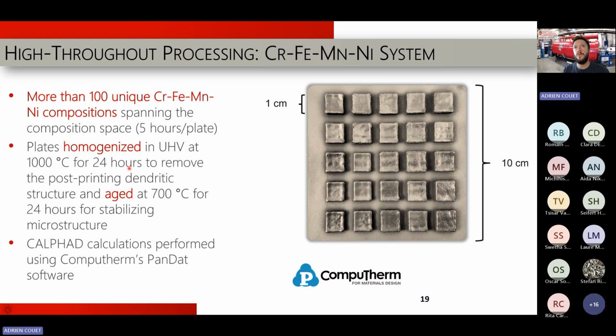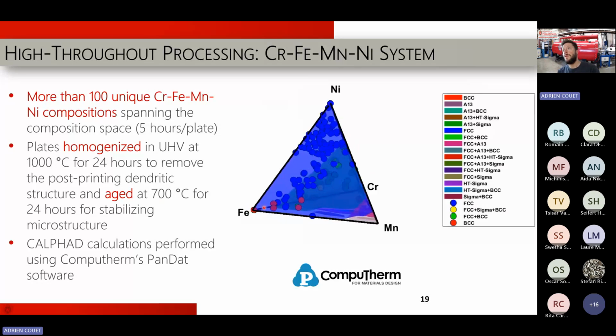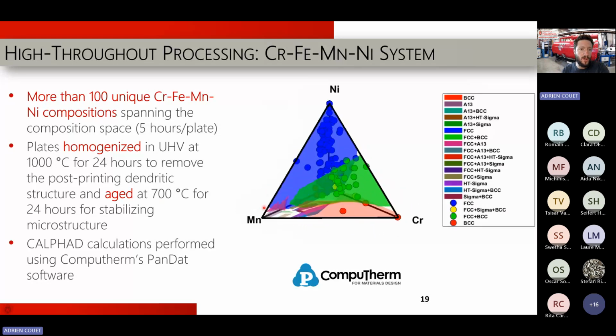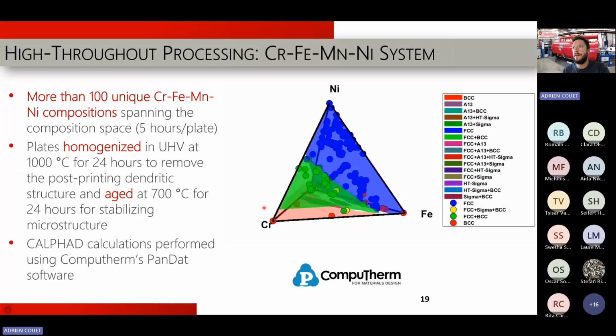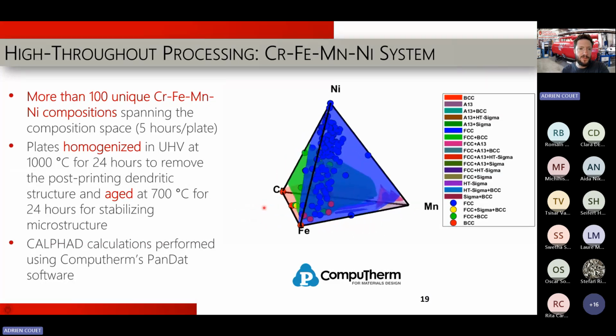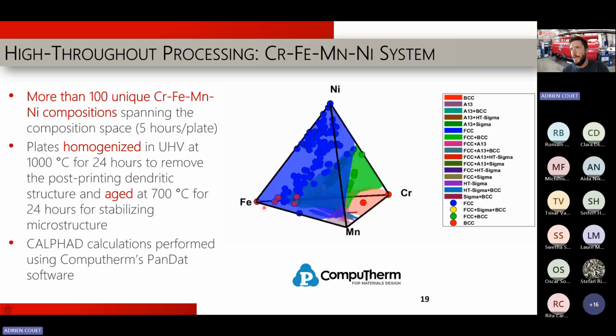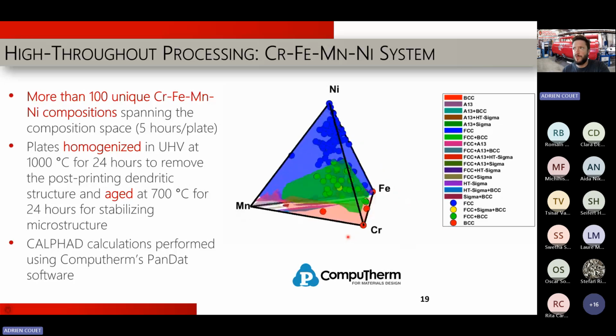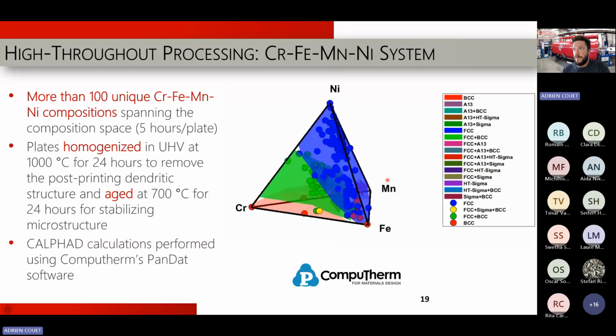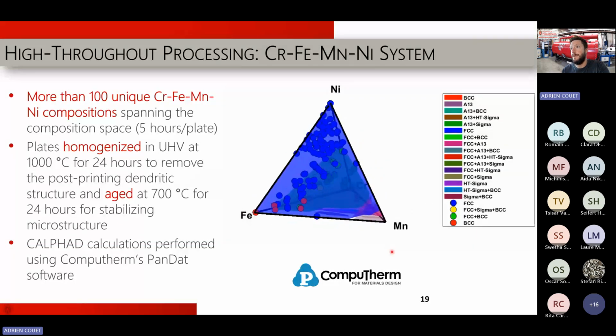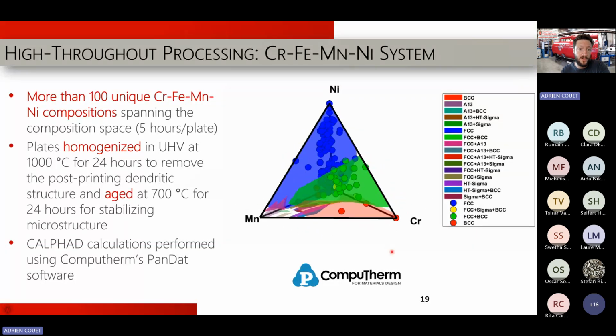And so we put those plates in for about 24 hours at 1,000 degrees Celsius to remove the solidification structure from additive manufacturing, and then we thermally age them at 700 degrees Celsius for 24 hours to stabilize the microstructure at relatively high temperature. Then we use CALPHAD to check what the expected crystal structure is. And we can also do XRD to check if those crystal structures are indeed the ones we observe. So we have about 150 alloys we've produced in this tetrahedra here, and most of them are in the single phase with high nickel content, because they are more printable, and also high iron content.